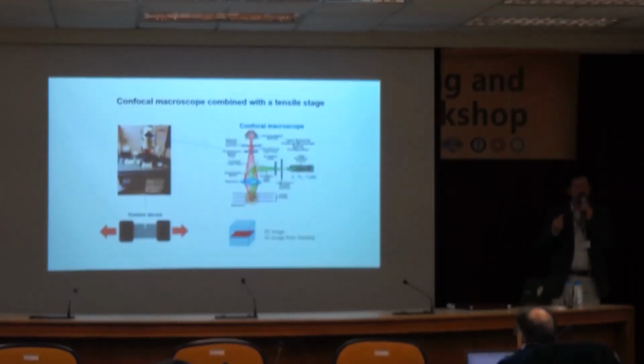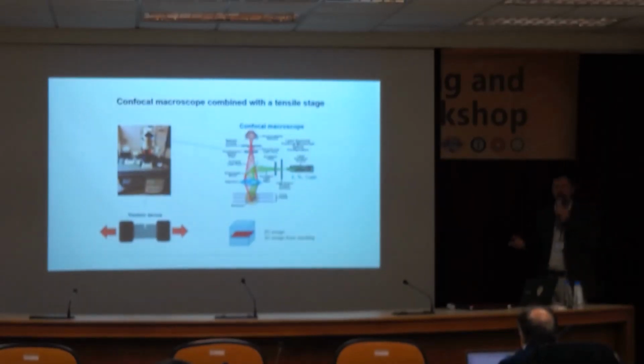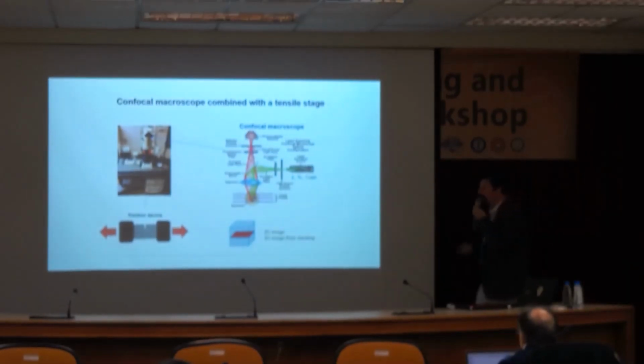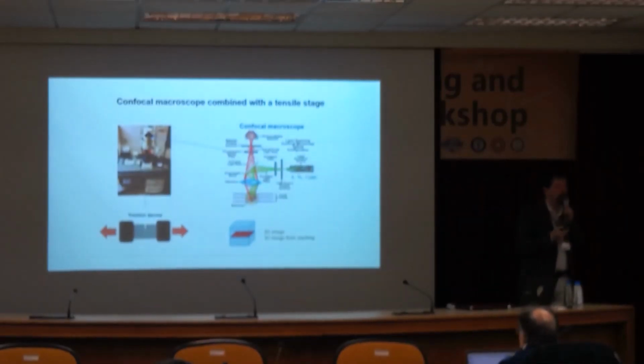Of course, there are some issues: absorption, calibration. You have to correct for aberration if you want to get quantitative values of intensity. So it's a bit different than imaging. Usually biologists are interested in imaging. Here we're interested in measuring. So that causes few more complications, but it's not unsurmountable with proper calibration. It's possible to actually be quantitative.